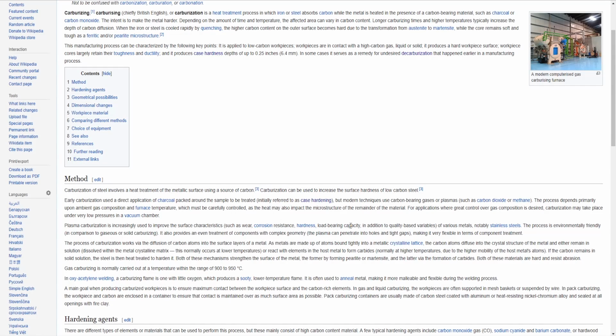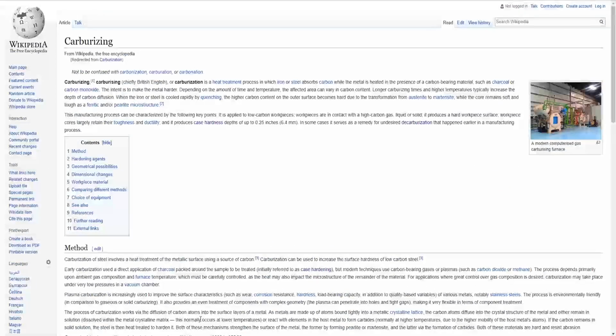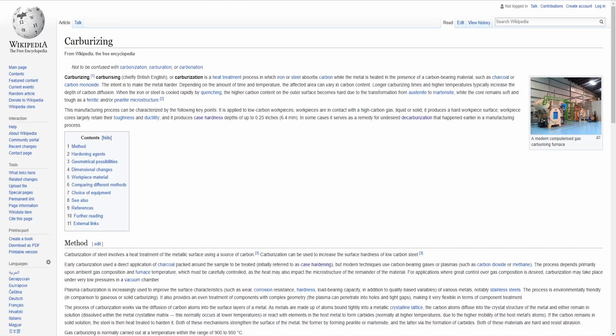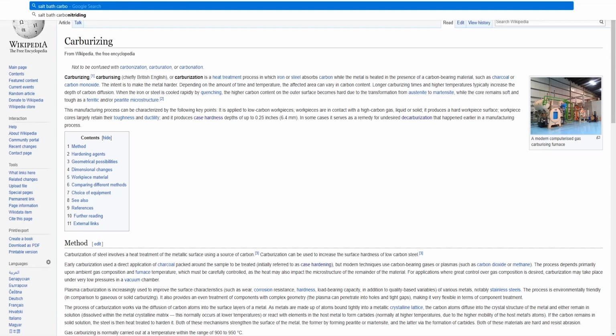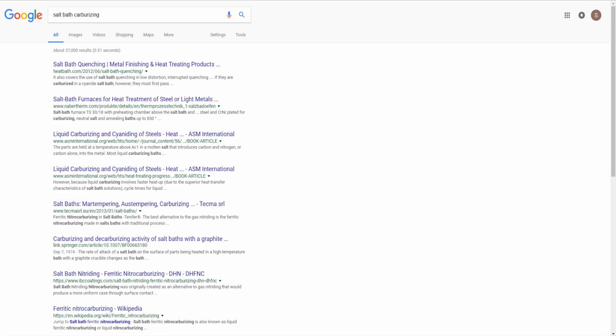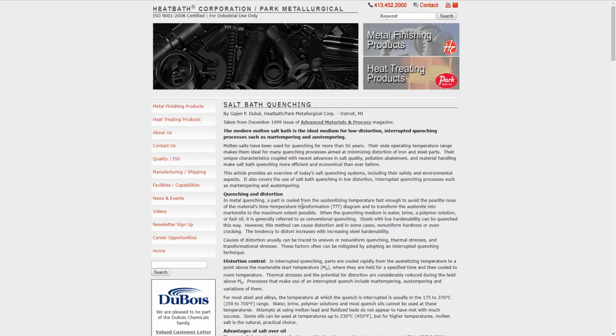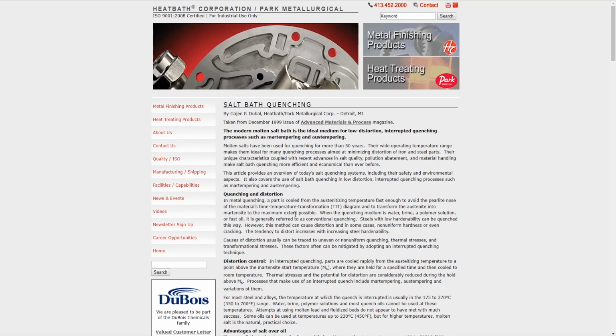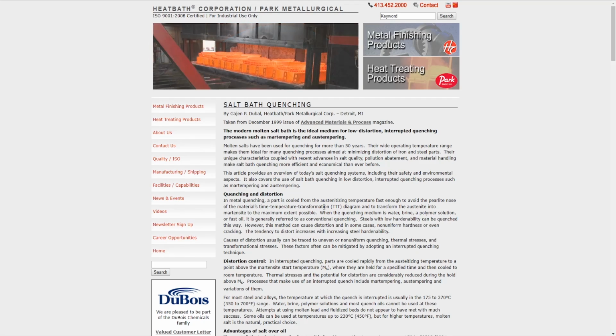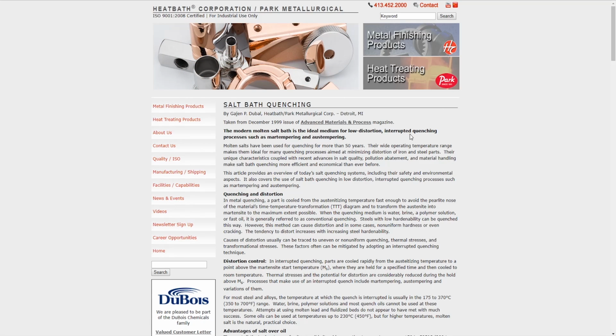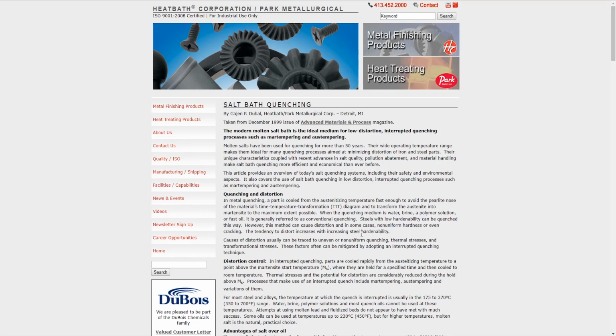So plasma carburizing is obviously way out of our range here. But they have another one, which is basically salt bath carburizing. So salt bath quenching, right? Basically, you cool from the austenitizing temperature fast enough to avoid the pearlite nose in the material's time-temperature transformation diagram, and to transform the austenite into martensite to the maximum extent. It's like a nose shape with a backward slant, and you have to drop the temperature of the steel so that it misses the nose.